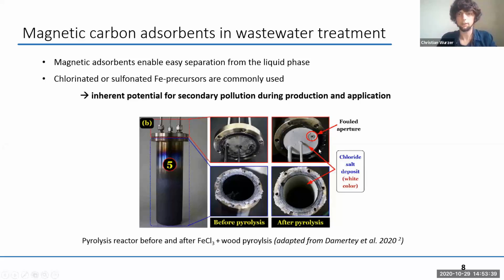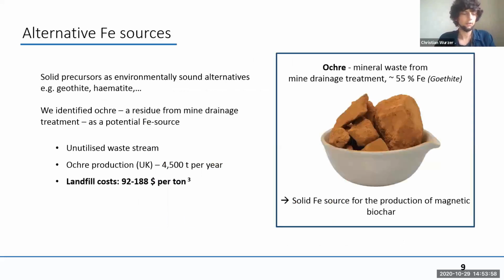So either the chloride ends up in your pyrolysis reactor, which can cause several issues, or in the gas emissions, or in the worst case, on your biochar adsorbent, and will be released into the water phase when you apply it in the water. So alternative iron sources are solid precursors. So natural solid precursors, for example, goethite or hematite. And in this study, we identified ochre, which is a residue from mine drainage treatment, as a potentially even more sustainable iron source, because you use a currently unutilized waste stream.